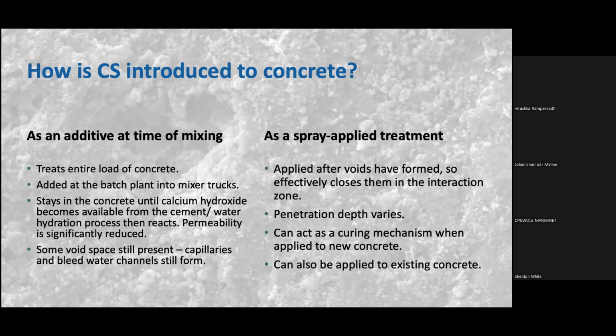If you were to ask me what the best way to use colloidal silica is for durability and waterproofing, I'm going to tell you that a spray applied treatment is the way to go. And the reason is that we allow those voids to form naturally. And then we apply about the time you can walk on the concrete is when we apply the colloidal silica. It penetrates deeply. And the least we've ever seen, for instance, is around 38 millimeters on a 100 millimeter slab. That's the least we've seen. Now, we often see much more than that.